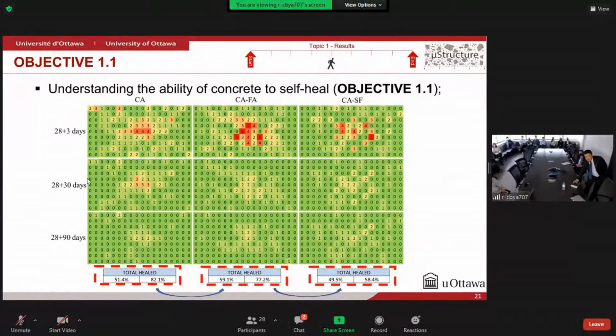However, as we can see here, the combination of crystalline admixtures with SCMs decreased this ability to self-heal. But on the other hand, the highest decrease in the compressive strength loss was in the mixture in which we have SCMs and crystalline admixtures. So why did we have that? To try to explain this behavior, let's use the second parallel research, in which we evaluated the changes in ASR gel due to the high volume of SCMs.